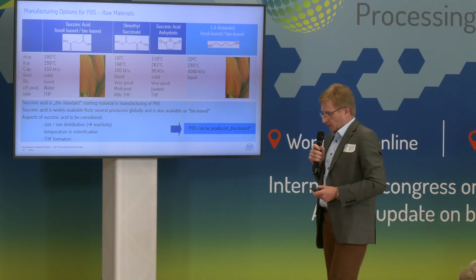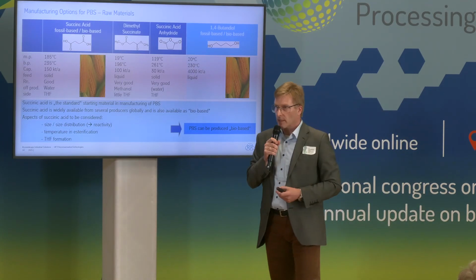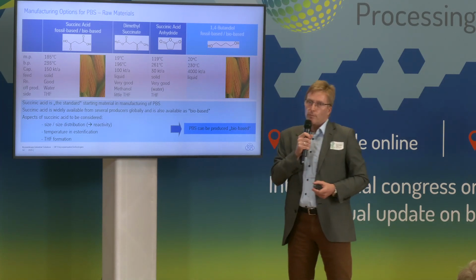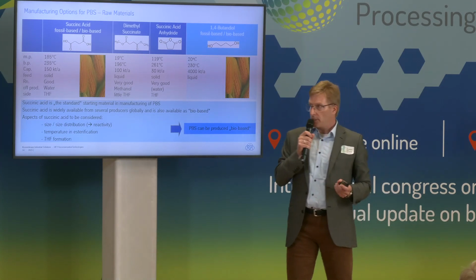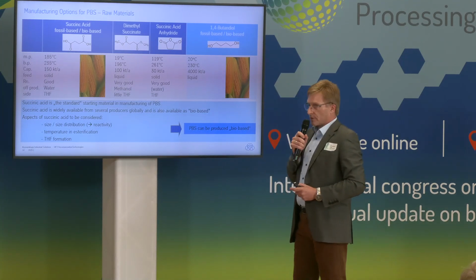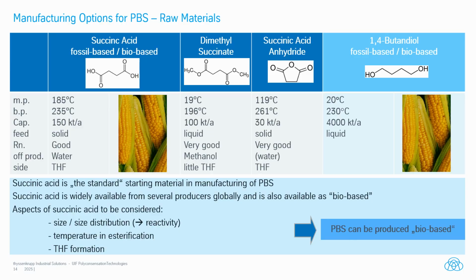Coming back to the monomers you need for manufacturing of PBS. I said typically you would make the PBS from succinic acid and BDO. But there are also alternatives available for succinic acid. I said DMS, dimethyl succinate, is an alternative, or even the anhydride can be an alternative. All of these chemicals are available in sufficient quantities, more than 100 kilotons a year, which is sufficient to make a lot of PBS in the future.